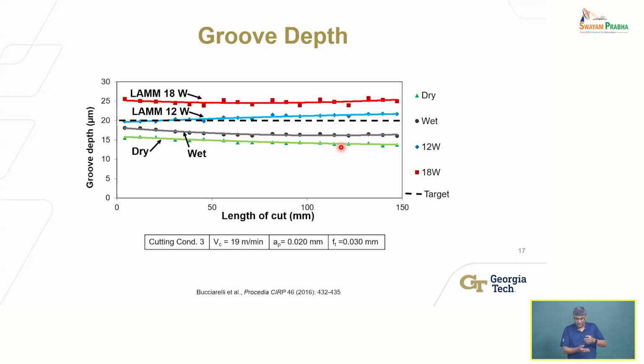The other source of error in this case is that under dry conditions, the tool is also wearing. Forces are high. The tool may be deflecting as well, right? Some deflection may be there. But under wet conditions, you can see it got better. It's closer to 20, but still not at 20.